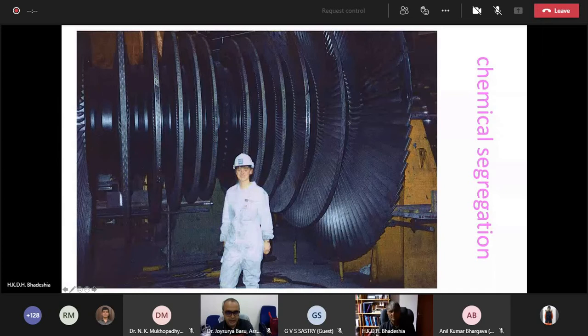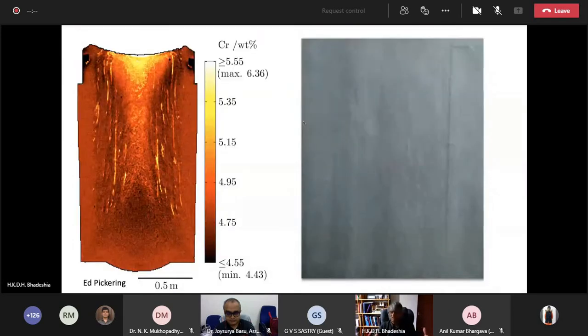Now, when you make large objects, they will contain chemical segregation because you cast them, and there's no way in which you can get rid of long-range segregation by homogenization. So if you look at this ingot, there's quite a lot of segregation. The scale here is 0.5 meter. Now, this is also a very large component, and you can see that there is almost no segregation. Now, how has this been made?